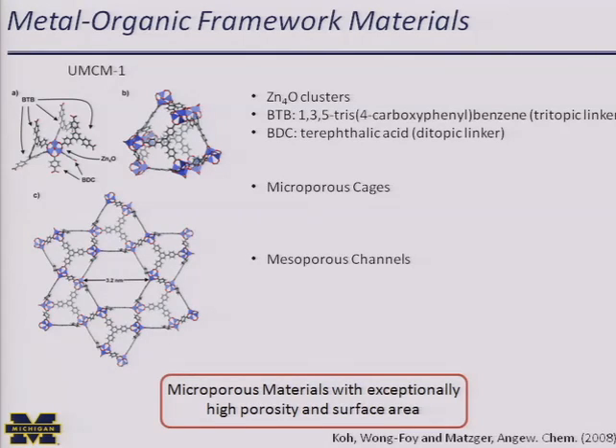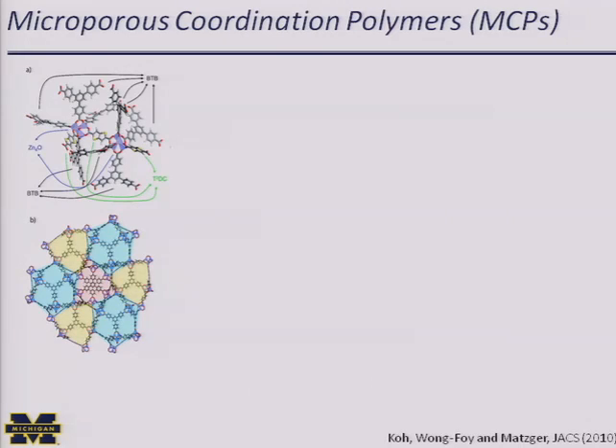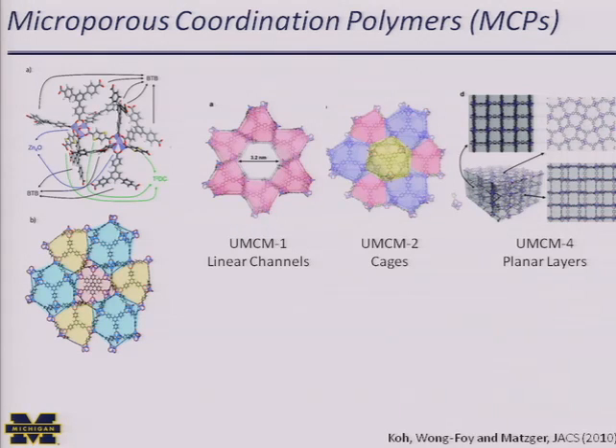So we can make different types of metal organic framework materials, or as they're called at University of Michigan, microporous coordination polymers. This is a subclass of MOFs. We could change the linkers or change the ratios. So this material here is called UMCM2. It only has BTB linker, it has BTB and TDC linkers now. And this forms only these cages, but no channels. And a whole class of materials have been invented at Michigan. So this UMCM1, as I discussed before, has linear channels. UMCM2 has these just cages. And then UMCM4 makes planar layers without any barriers within those planes. And I'll talk to you a bit about what diffusion characteristics come out of that.